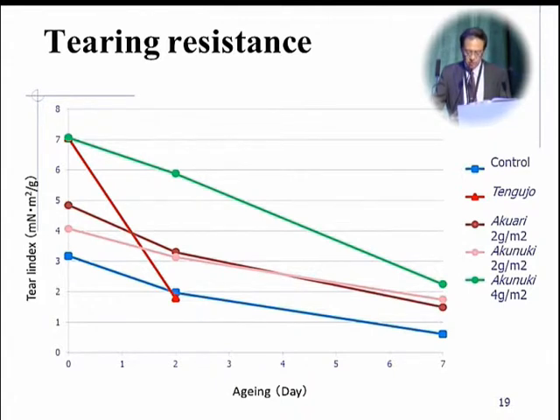With paper strengthened by means of the fleece method, using coarse fiber 2 grams, we observe an increase in tearing resistance just after treatment and after accelerated aging, but there is no clear difference between the two pulp making processes, Akuari and Akunuki. Paper strengthened with the fleece method using coarse fibers, 4 grams, showed higher tear resistance on day 0, 2, and 7. Paper strengthened through application of a Tengujo sheet didn't produce satisfactory results.